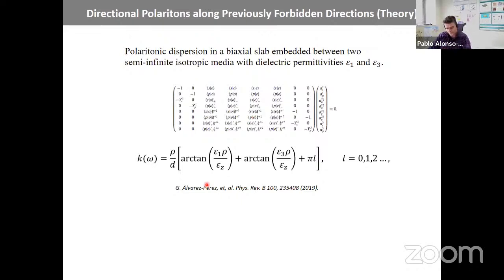First, let me tell you that these polaritons that I show you in molybdenum trioxide, which is a biaxial material. It's super anisotropic. We saw that in the literature there was no theory paper where it was treated in a proper way. So we had to do this analysis because of these ordinary and extraordinary waves that happen in biaxial media. One faces really difficulties in the analytical study, but we were able to do some assumptions and finally get this kind of a compact equation that explains the propagation of polaritons in biaxial media. Here there are some terms, epsilon1 and epsilon3, which are the permittivities of the superstrate and substrate, so it's where the biaxial slab is embedded. There is also the thickness.